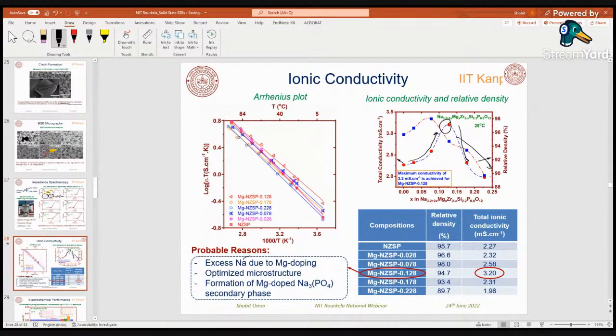This will also have an effect on the conductivity that you are observing for 0.128. So you can see there are compounding effects of various factors: density, secondary phases, primary phases which are forming, and the magnesium and sodium amount present inside the crystal structure. That will have an effect on the conductivity that we have obtained. But you can see that we are able to consistently obtain a conductivity of 3.2 millisiemens per centimeter. We started from 1 millisiemens per centimeter, but we are able to achieve 3.2 millisiemens per centimeter at room temperature, and that is also using earth abundant magnesium.